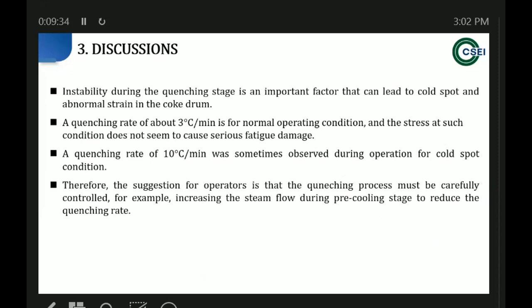And we also know the instability during the quenching stage is an important factor that can lead to cold spots and abnormal strain in the coke drum. And we simulated the normal operating condition. The quenching rate is about 3 centigrade per minute, and for the cold spot condition, we found during the actual operation history that the quenching rate can sometimes reach 10 centigrade per minute. So the cold spot effect really exists during the operation.